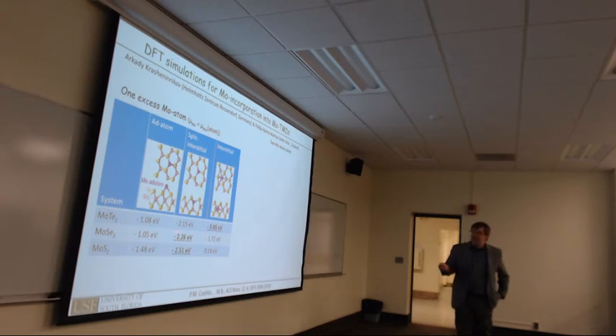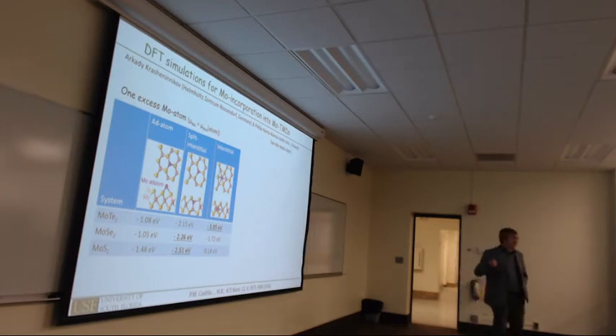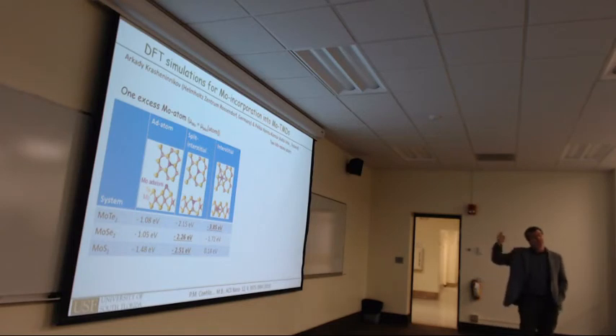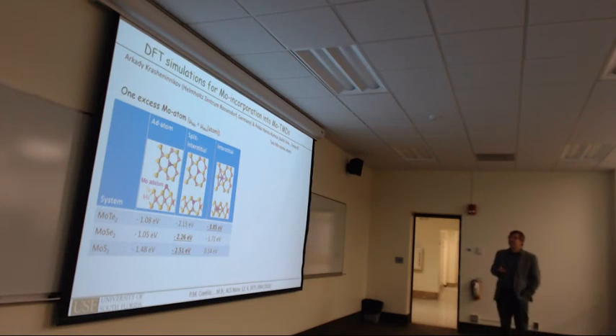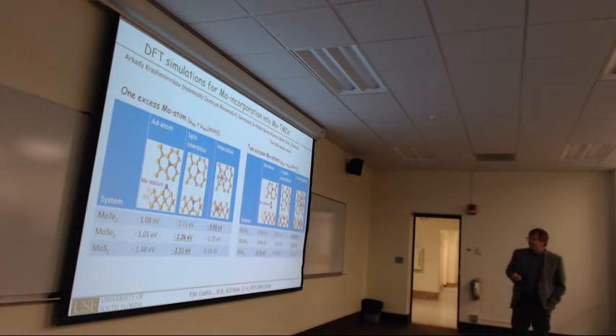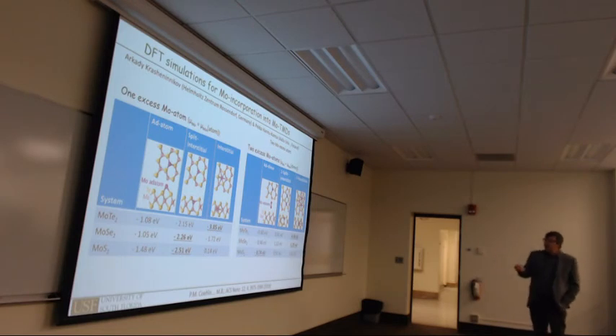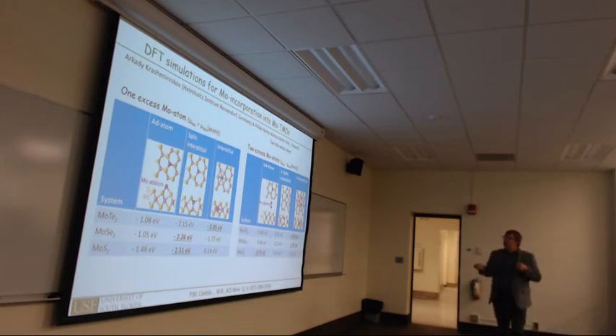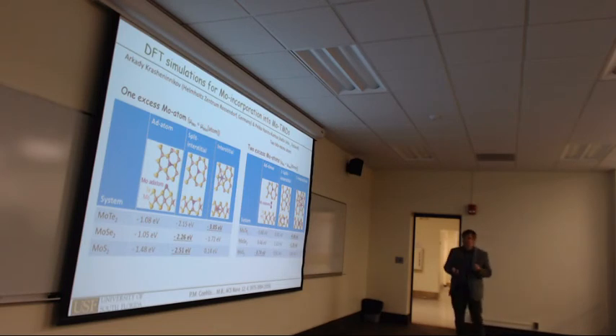Now, for molytelluride, it's very clearly preferred to form an interstitial, while for a single molybdenum atom, actually the split interstitial is favored in molyselenide and molysulfide, and the adatom is not favored at all. It's big. So if you put molybdenum on top, it really wants to go inside the layer. Now, if you add a second molybdenum atom, both molytelluride and molyselenide like to form these interstitial sites and 2 molybdenum atoms next to each other. And for molysulfide, the dimer becomes favored, so it does not go in the layer anymore, and it's kind of the starting point of the nucleation of a cluster.